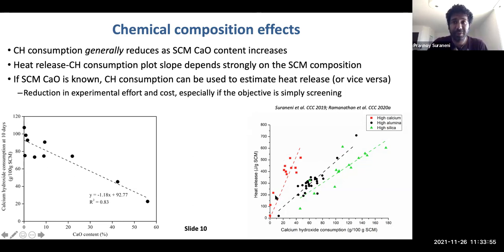So in principle, if all you're interested in is estimating or screening different materials, then if you know the chemical composition, you can say, oh, my material is either here, here, or here. And then you can just measure one parameter, which is the heat release or the calcium hydroxide consumption. And you can use that to estimate the other one.